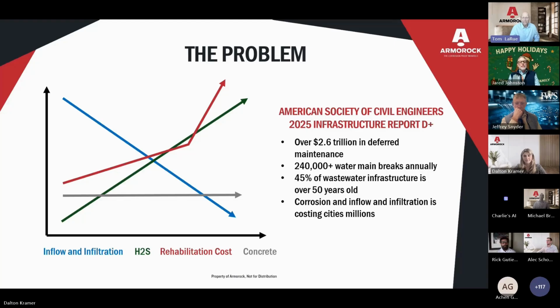But the result of that is the concentration of the effluent flowing through the system increased, leading to an increased concentration of H2S gas. As the parts per million of H2S within the system increased, the susceptibility, the likelihood of corrosion also increases. Portland cement will begin to corrode as the ppm of H2S gets over 10 ppm, which is not a very high level. So it didn't take much reduction in I&I to really see upticks in the rate of corrosion. So as the H2S levels have increased, the rehabilitation costs have also increased. And this is a multifaceted problem because, again, the H2S levels are increasing, and the age of the systems is increasing. Over 45% of wastewater infrastructure is over 50 years old.